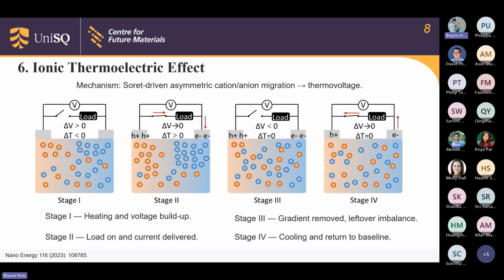Stage 3, gradient removed, leftover imbalance. When the temperature difference goes away, the stored concentration difference can drive a small reverse voltage for a short time until the ions remix. Stage 4, cooling returns to baseline. During cooling, the polarity returns to the original sign and the voltage decays to zero as the system relaxes.